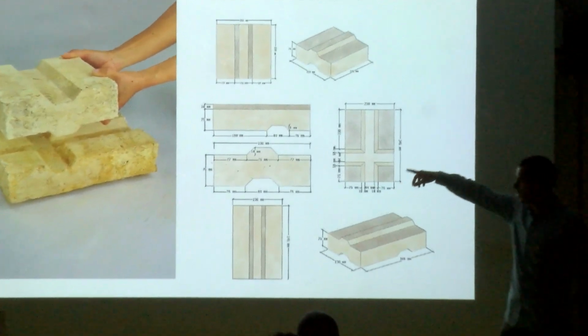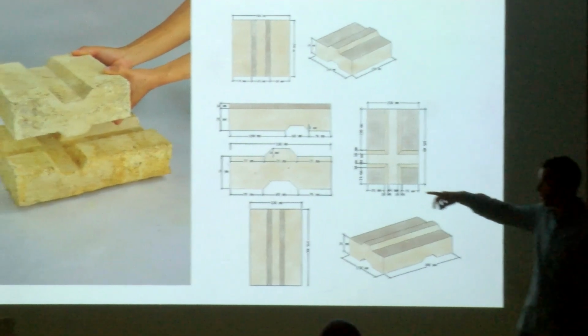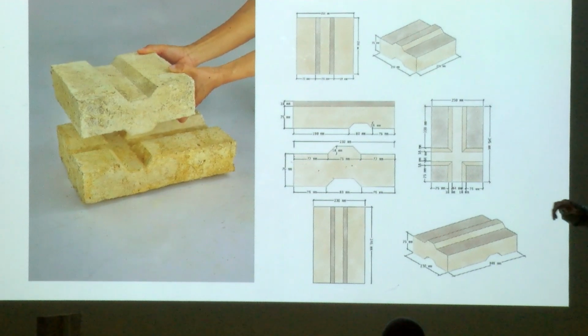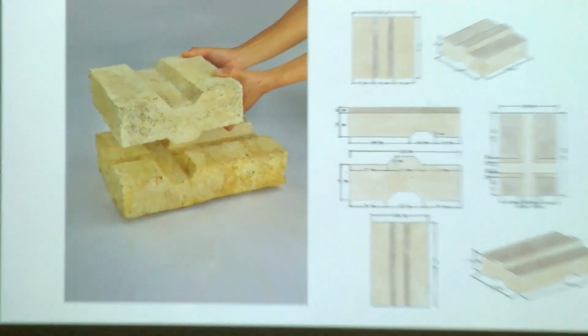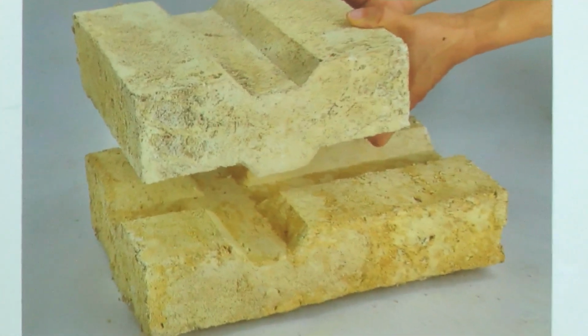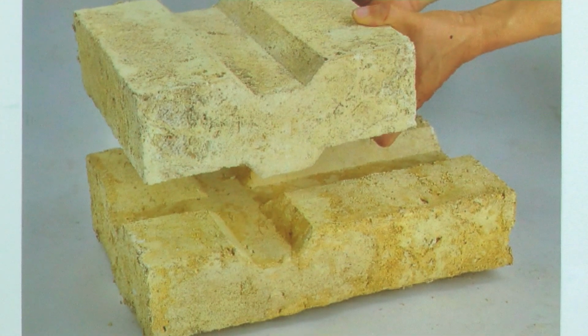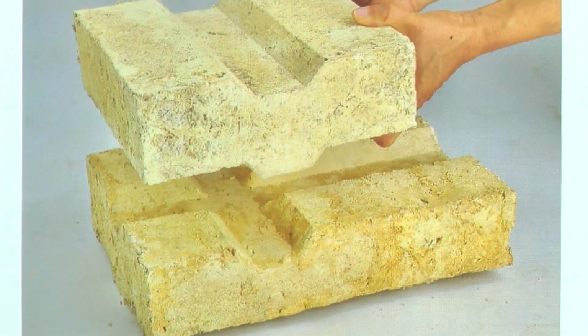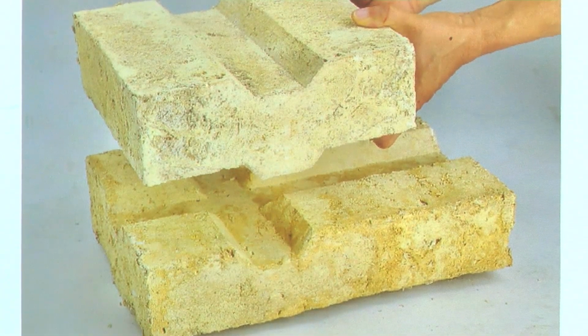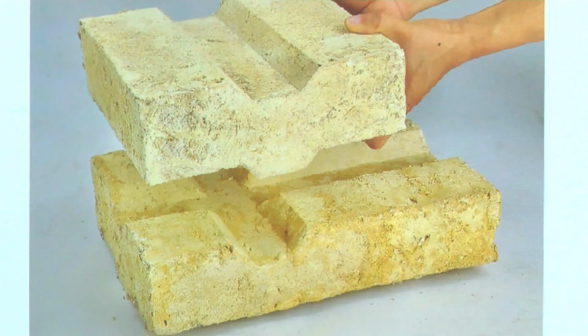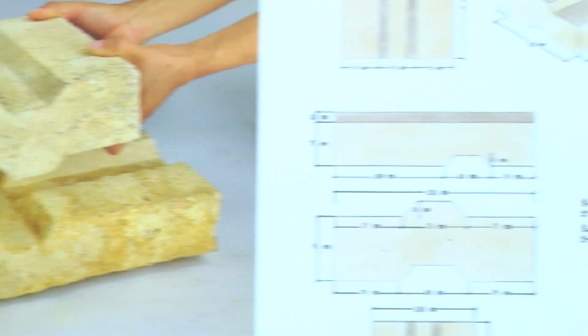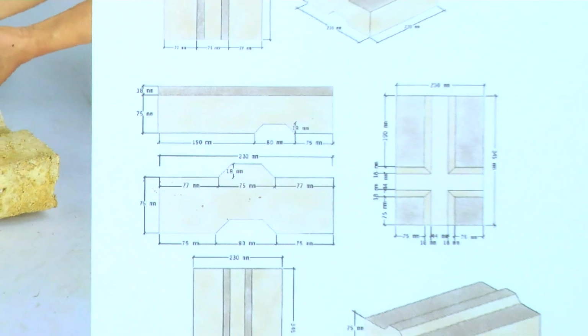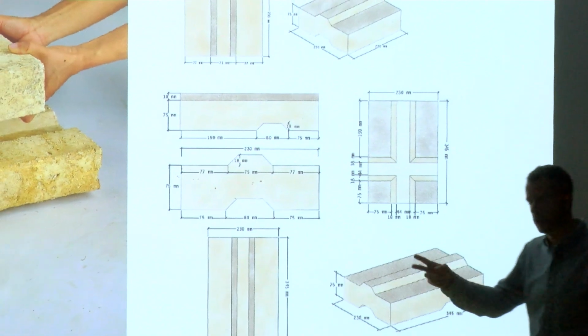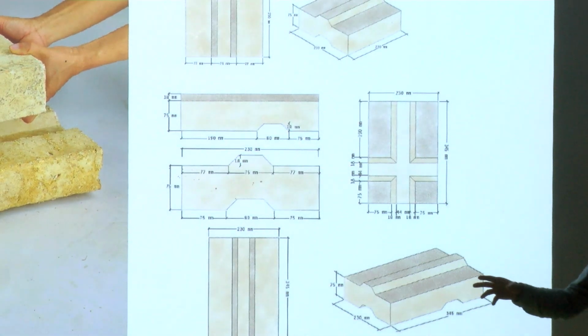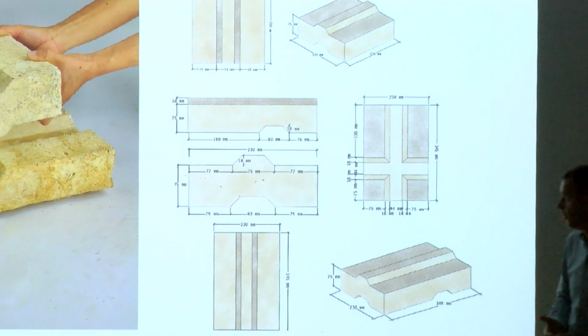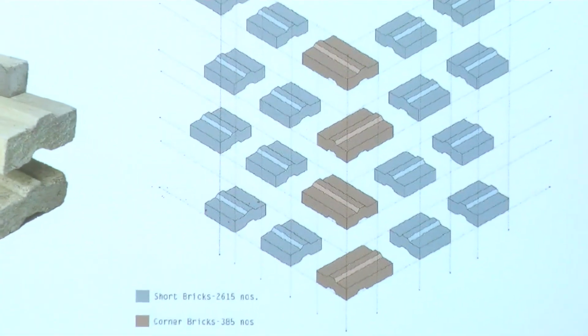And then we had a corner block, which had a cross for the intersection that resolved the corner condition, and also resolved it when we were reaching a window or we wanted to end the wall. You didn't need to cut a brick by half, you were just using the lower block, which is 1.5. So just with 2 geometries, we were able to resolve the whole building, which means that you only need to invest in 2 molds, and you only need to explain that you have 2 typologies to workers on site, which was also fundamental for the success of the building.